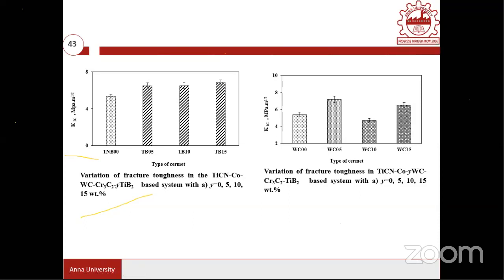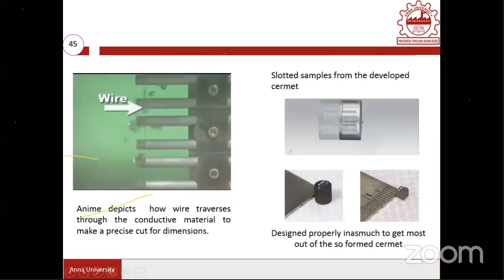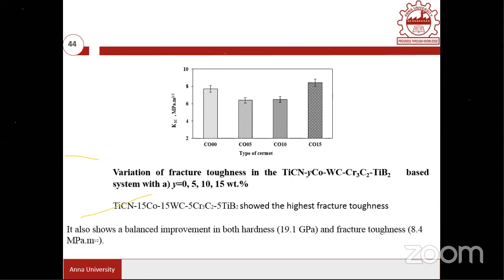And in terms of varying tungsten carbide, it is sometimes giving close to 8 megapascal root meter. And in case of the cobalt value, it is giving really more than 8 value. So for example, cobalt 15% addition with this composition, TiCN, tungsten carbide, chromium carbide, and titanium diboride, where you have this. So by looking at this hardness value as well as toughness value, okay, so now considering this, we have